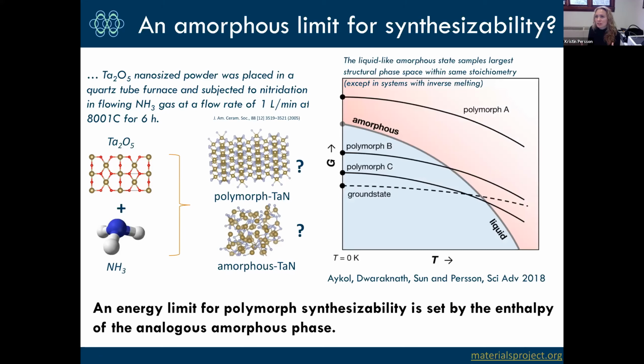If you sketch the thermodynamic Gibbs free energy of different polymorphs, and you estimate the Gibbs free energy or the enthalpy of the amorphous state, we can calculate the enthalpy for the polymorphs pretty well. We can approximate an enthalpy for the amorphous state by scrambling the atoms in different boxes, making sure you get the right density, and then calculating different snapshots of different amorphous states and averaging that. That gives us at least an idea of the enthalpy of the amorphous state. What we can assume is true is that the amorphous state, which has a highly increased disorder and is almost a liquid-like structural state, frozen, should have a much larger entropy than any of the other ones.